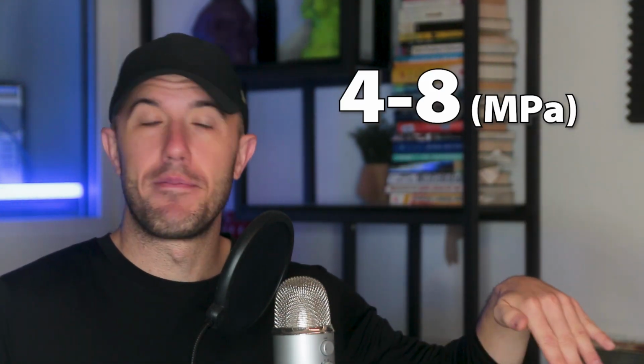lot. But if you actually look at the tensile stress of these parts, you end up with a range of between 4 and 8 megapascals. And this is interesting because even though these parts were 3D printed and the layers are having to stick to each other, the actual tensile stress of this type of TPU is expected to be about 8 megapascals. So within our tests, we are able to reach 100% of the strength of an isotropic material, even though it's 3D printed and the layers are having to stick to each other.